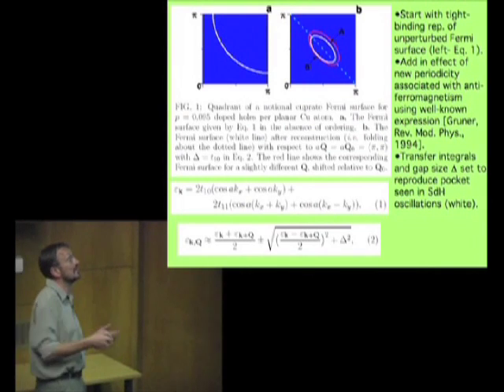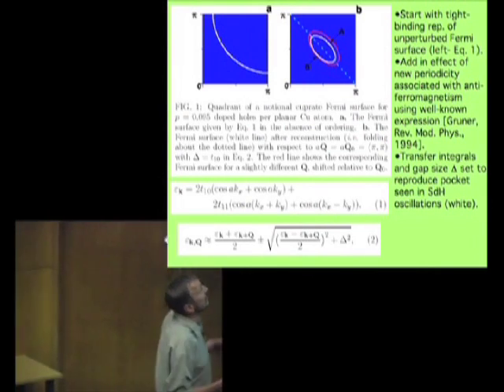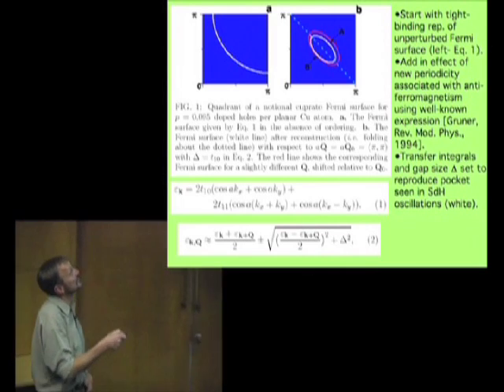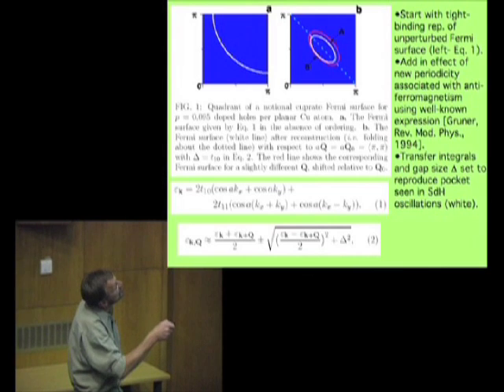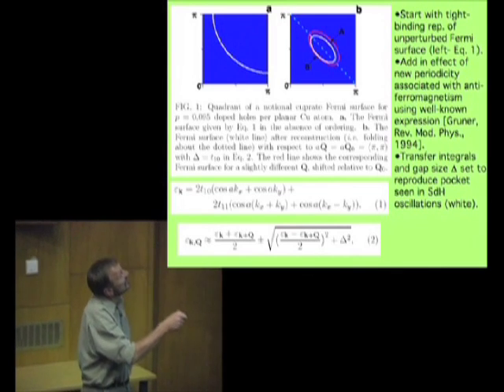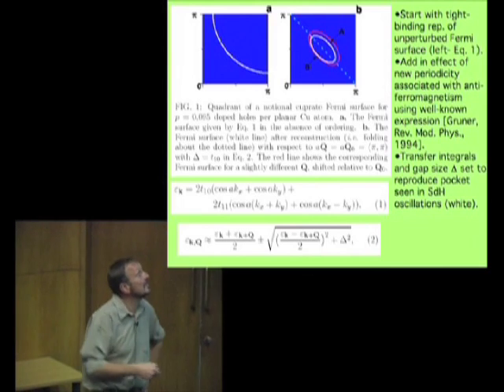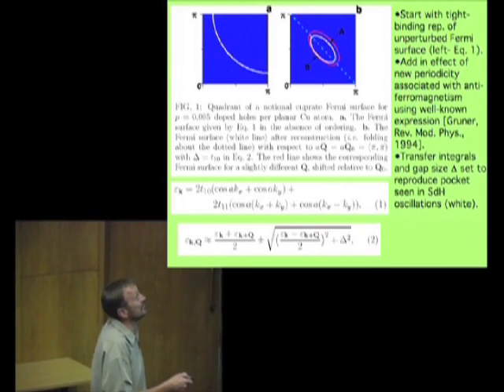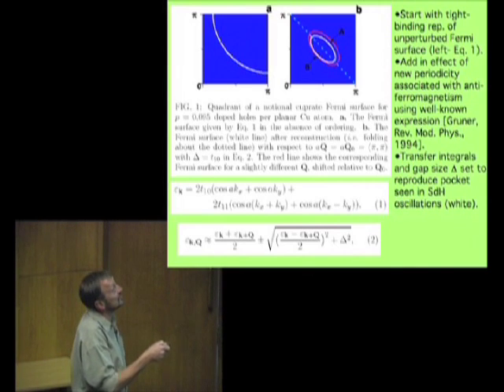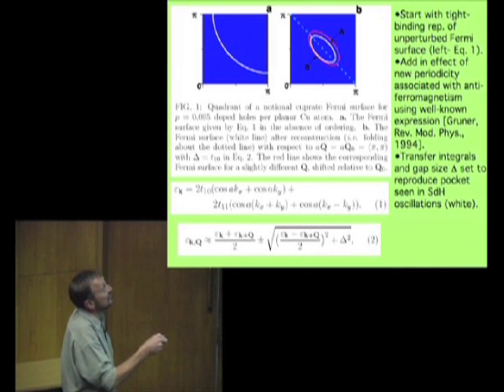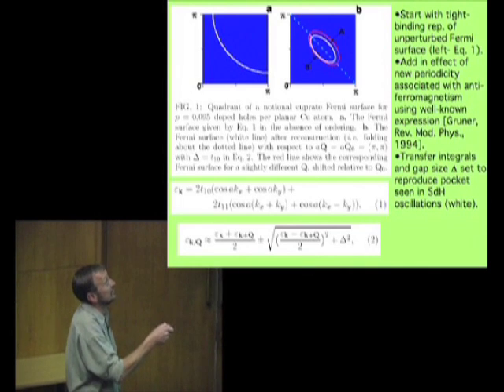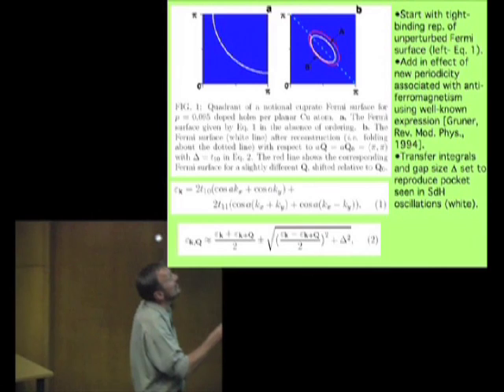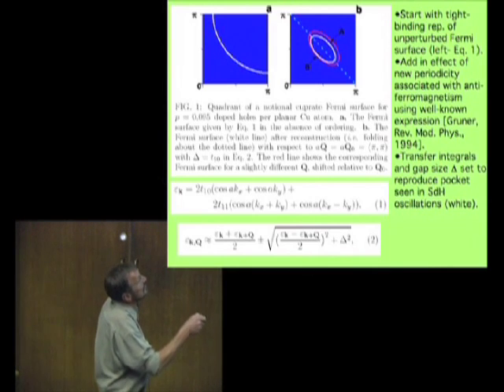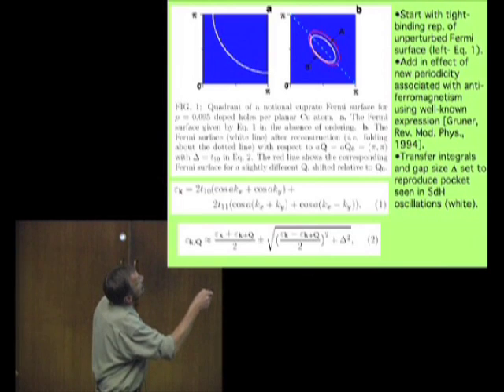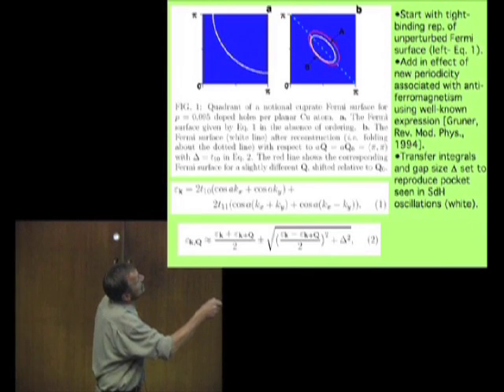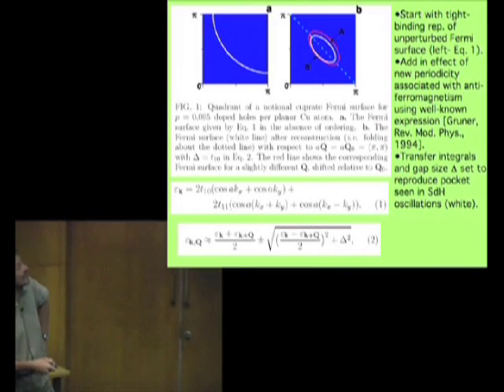Well, we can try to understand that by modelling what's actually going on in making this new pocket out of the original band structure. So here is the original Fermi surface, the electronic band, in a simple model, this thing down here. When we introduce the new periodicity due to the antiferromagnetism, we basically introduce a new plane about which we've got to reflect the Fermi surface. This is this wave vector Q that I mentioned before, to produce the new Fermi surface. So this point here is just taking a diagonal like this and reflecting the original piece of Fermi surface in it to make the new Fermi surface, which is the white pocket that you see there.